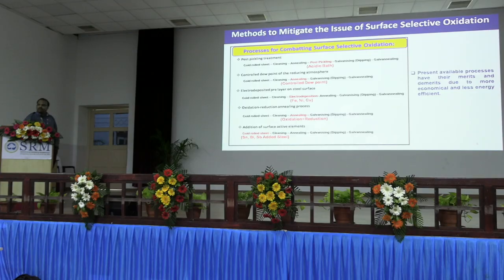Different industrial practices are being used to mitigate this problem, which include post pickling treatment, controlled annealing treatment with a controlled dew point, application of a pre-layer using electrodeposition methods such as iron, copper, nickel, application of a simultaneous oxidation reduction process, and addition of active alloying elements. But all these processes are applicable for particular grades of steels and particular compositions of the galvanizing bath.